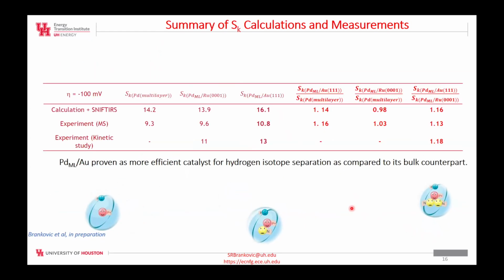And so in summary, you can see that these ratios are fundamentally the same from different types of experiments where we measure separation factors, whether we use spectroscopy and calculations, mass spectroscopy experiments, or kinetic data. We are getting about identical advantage of the palladium monolayer on gold as compared to bulk palladium or palladium monolayer on ruthenium. Therefore, the theory and idea is proven to be correct.